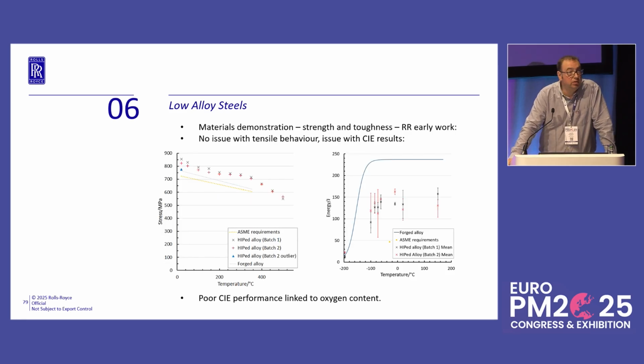Our early work, like everyone else's, showed, as expected, that getting the strength is no problem. The powder HIP material is really, really good. And on the left there, you can see the tensile data across the temperature ranges. The crosses and the plus and minus are the two batches that we had made. The ASME requirements are aligned, so we're well exceeding them on the strength. Elongations and reductions in area are all fine as well. So everything's looking really good.